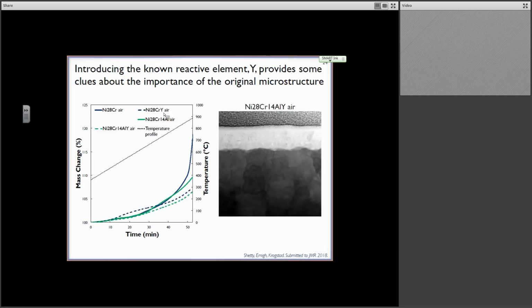Now, if I add yttrium to both of these thin films, both of the curves actually drop significantly. All right? So not just the one with aluminum, now both of them, even the one with just chromium, the oxidation resistance is much better. And so we're going to look at the microstructure over here of the high aluminum concentration with yttrium that's been oxidized in air. So we didn't take any efforts to oxidize it slowly. This is done in air.